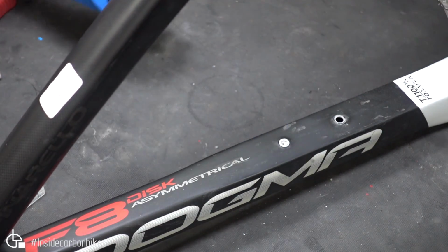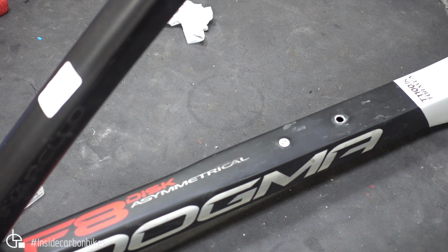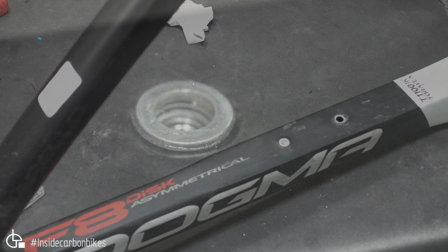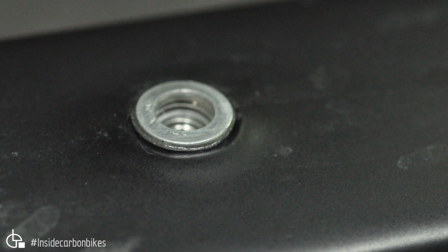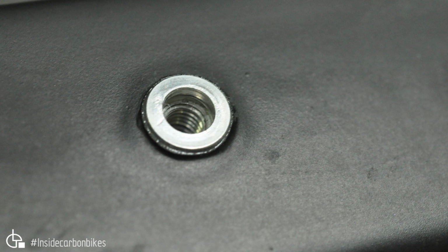Now, on a down tube with a water bottle above it, you are going to get corrosion. So if you want to avoid those problems, you need to put the adhesive in there, and also treat the insert as best you can to avoid corrosion. This is what the final part will look like fitted. As you can see, much better than what we started with. It's all nicely bonded, secured. It's been protected against corrosion, and it's going to have a much better life than what was originally done at the factory.